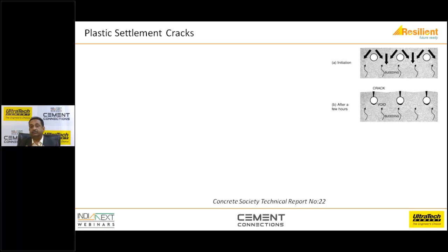Now, this is different from plastic shrinkage cracks. This happens when the concrete settles immediately after vibration, and the bleed water comes to the surface, and the cement and aggregate settle down. And there is a restraint to this settlement. When I say restraint, it could be in the form of reinforcement, or it could be a change of section. And immediately above that, you will find the cracks to develop.